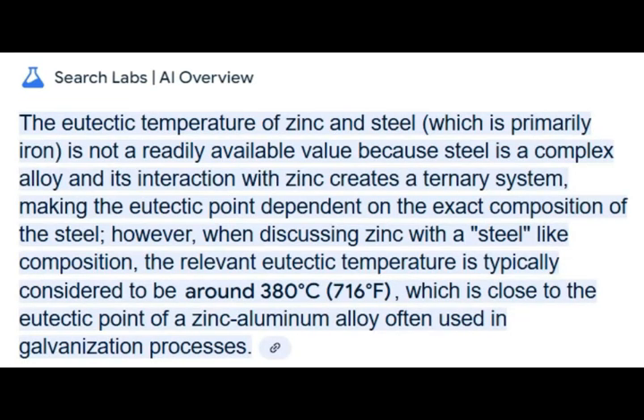The eutectic temperature of zinc and steel, which is primarily iron, is not a readily available value because steel is a complex alloy and its interaction with zinc creates a ternary system, making the eutectic point dependent on the exact composition of the steel. However, when discussing zinc with a steel-like composition, the relevant eutectic temperature is typically considered to be around 380 degrees Celsius, 716 degrees Fahrenheit, which is close to the eutectic point of a zinc-aluminum alloy often used in galvanization processes.